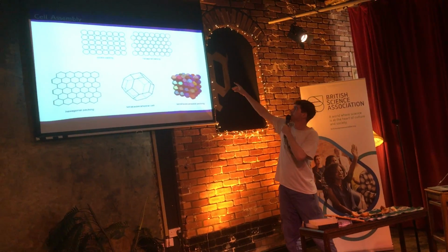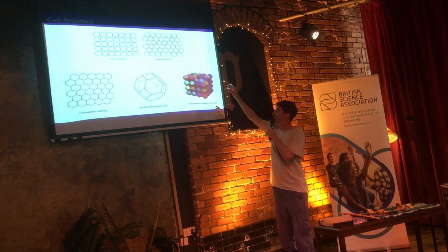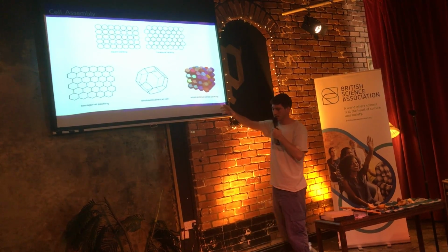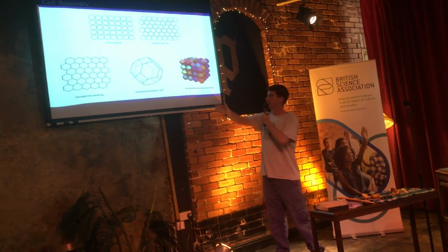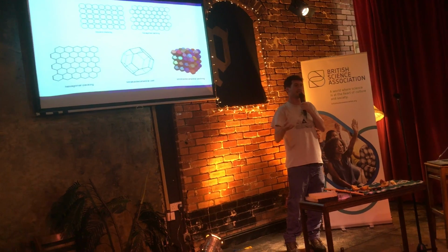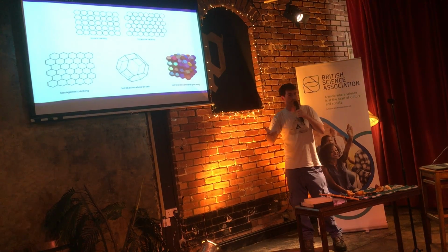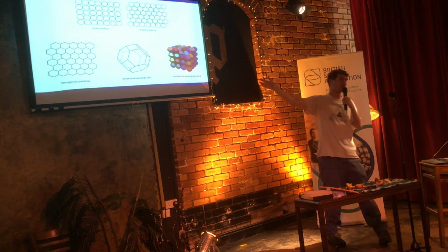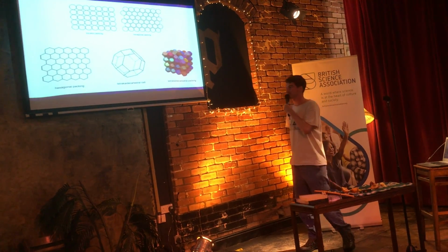Now, here we have a point contact between each of the circles. If we were to suck out all of that extra airspace, we end up with hexagons. And hexagons are mathematically proven to be the most efficient use of the smallest cell wall material for the amount that it can store within it. And that's why bees use hexagonal patterns for their honeycomb. And this is the structure that I fundamentally study, what happens when this structure deforms.